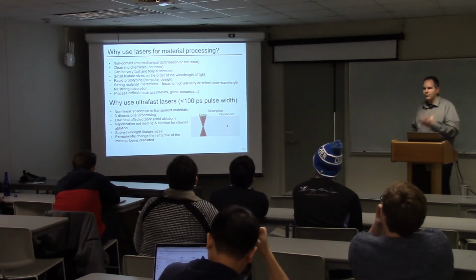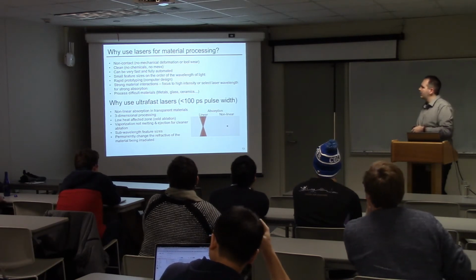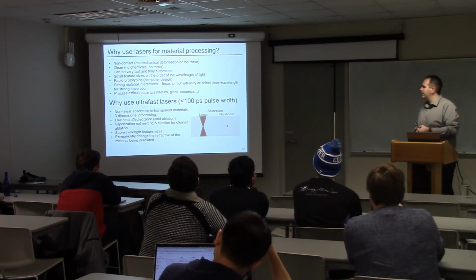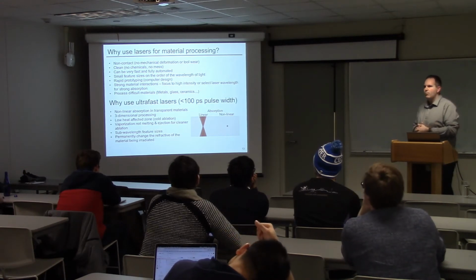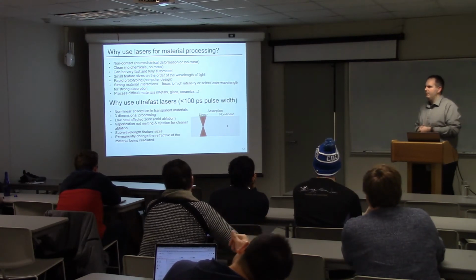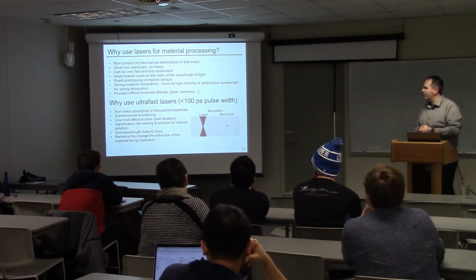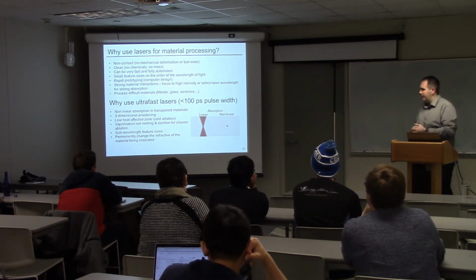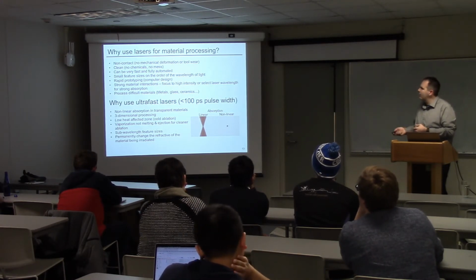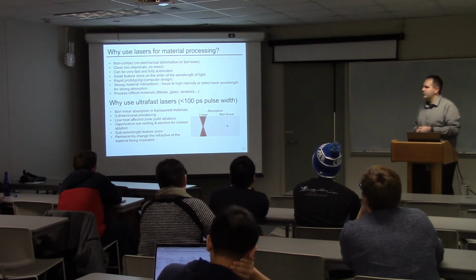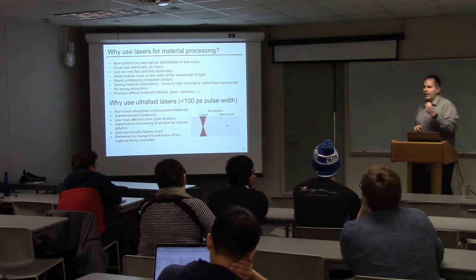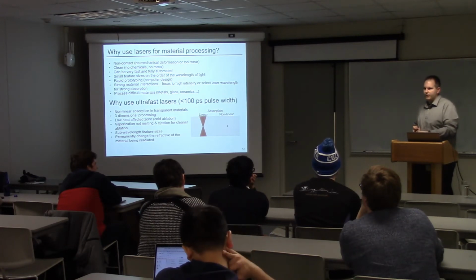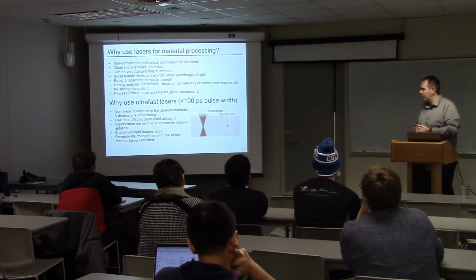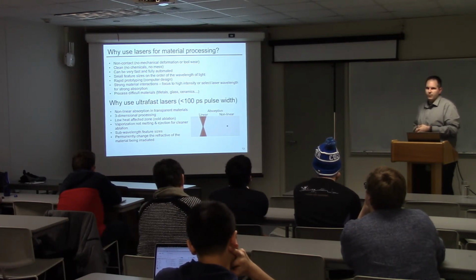I don't know the technical definition, but typically when one says ultrafast lasers, in the literature we see less than 100 picoseconds, more commonly 10 picoseconds and under, but there's some threshold, it's not so important where, but on this scale, let's say. What's interesting with ultrafast lasers, and we'll talk through this in the next few slides as well, is that you can have a nonlinear absorption. So you can make a wavelength that would not be absorbed become absorbing through some nonlinear mechanisms that we'll touch upon. And that allows you to do three-dimensional processing.